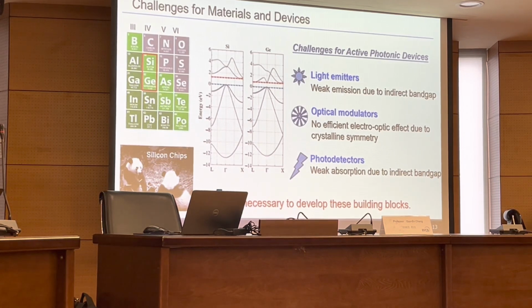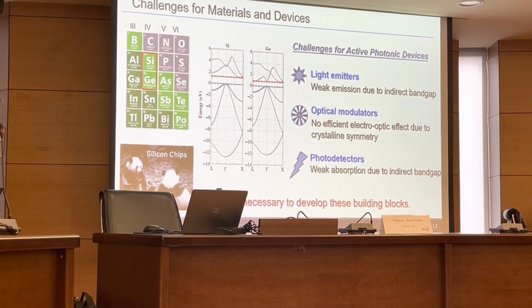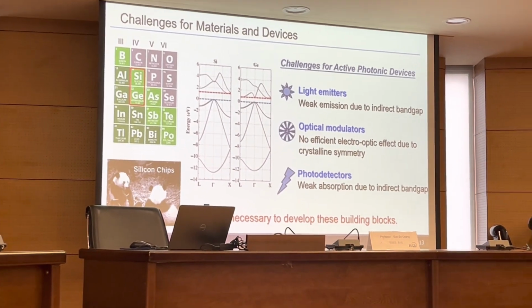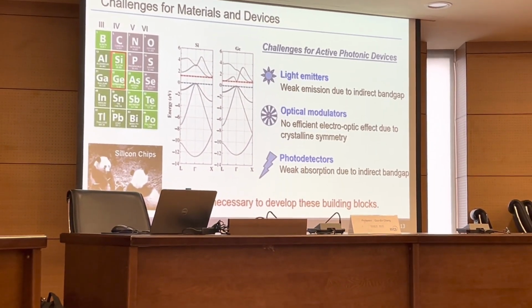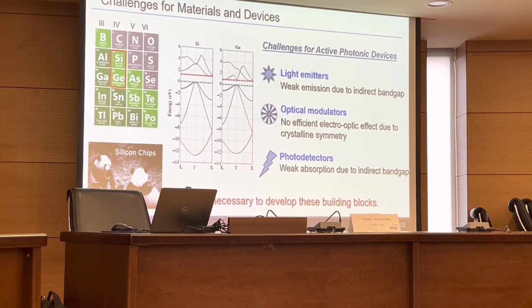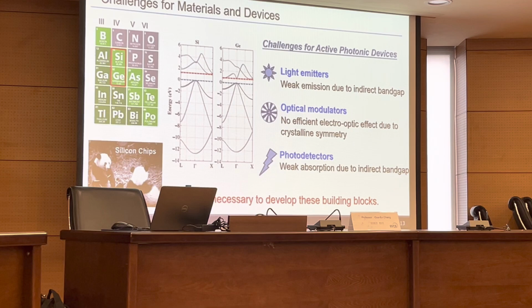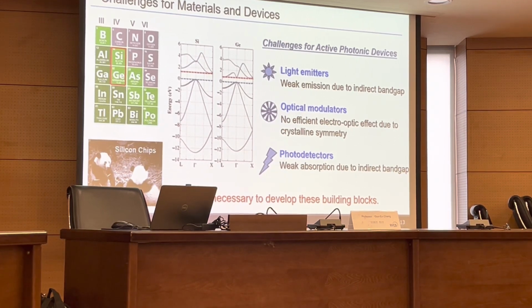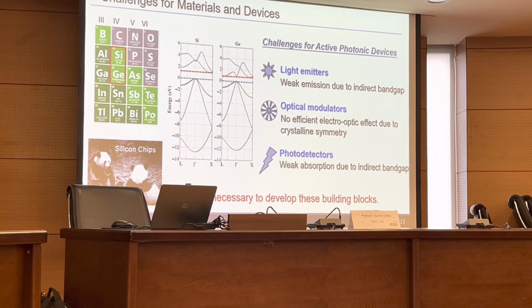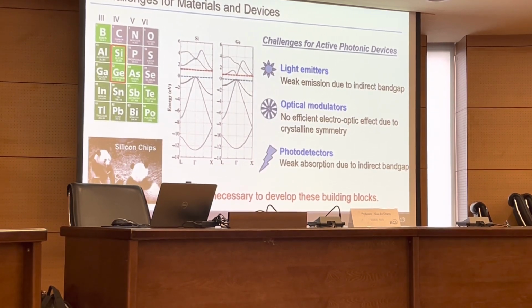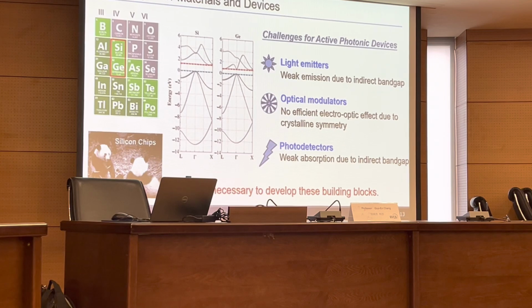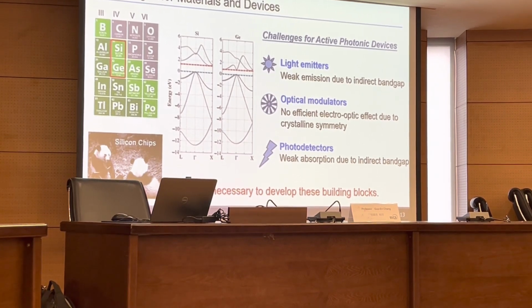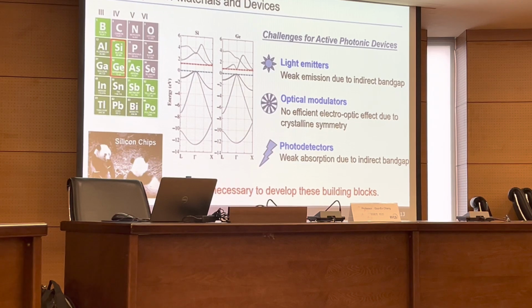For light emitters, because we cannot have direct transition, the emission efficiency is very weak. We sometimes joke that silicon is a dark material because it cannot emit any light. It also cannot have efficient optical modulation because there's no efficient electro-optical effect due to the crystalline symmetry. For photodetectors it's the same, since direct bandgap transition is prohibited, so the absorption is very weak.